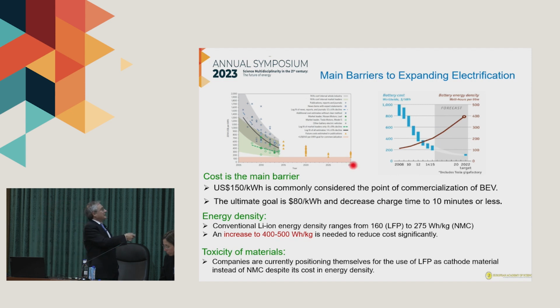Energy density. If we increase the energy density, obviously there is an effect, a reduction in the cost. So, considering that the conventional lithium energy density ranges at the moment from 160 watt-hour per kilogram using lithium iron phosphate to 275 watt-hour per kilogram if we use, for example, NMC oxide, nickel, manganese, cobalt, we can improve the energy density, but we also need to increase the energy density to 400 and 500 watt-hour per kilogram in order to reduce the cost significantly.